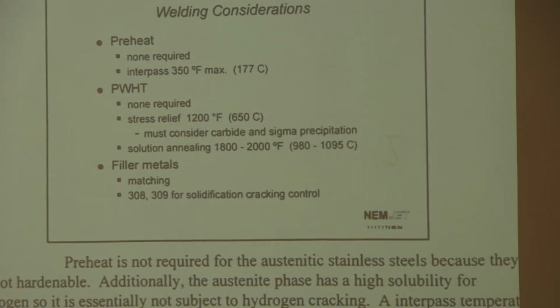Again, because they're not hardenable, there's not really a need to post-weld heat treat on the austenitic stainless steels as well. You can stress relieve if necessary, but you need to consider the carbides that could form, and you need to consider sigma and other phases, which are brittle phases that can form in these alloys.